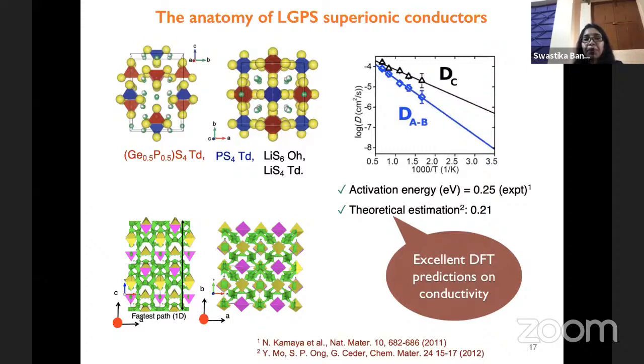And this is the framework which is actually interesting, especially for beginners. I would like to introduce you to the framework, and you will be really excited to see that this is a solid framework, a crystal kind of framework. You see, the arrangement is such that the lithium ions, the green color, and green and white says partial occupancy, are basically free to be mobile. So this is such an excellent framework. You have a static crystal framework, but you have a sublattice which is mobile.